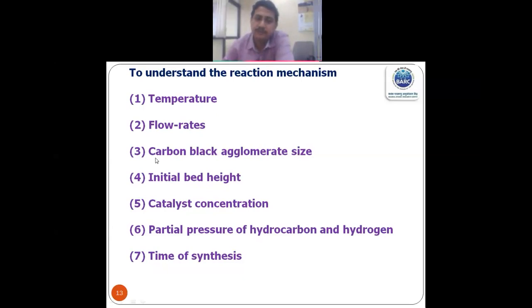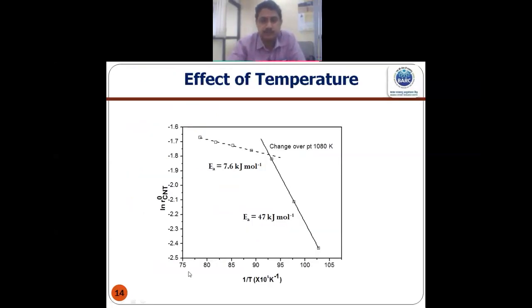Then to understand the effect of the internal diffusion, we need to vary the carbon black agglomerate size as well as initial bed height. Now the last two, fifth and sixth, that is catalyst concentration and partial pressure of hydrocarbon and hydrogen, this is required to vary in order to understand the chemical reaction control. And finally the time of synthesis gives us how the catalyst gets deactivated, because carbon is getting deposited continuously, and after some time the catalyst gets deactivated. So that idea also we can get from the time of synthesis.